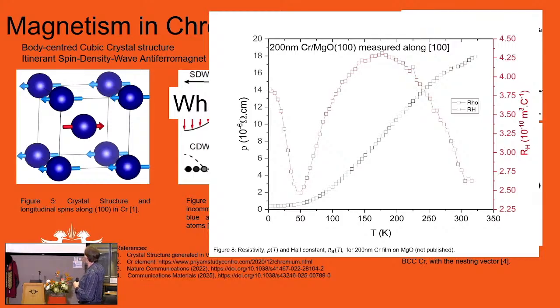And here we show resistivity, so current and voltage with a particular geometry. That's very important. But as you cool down, you take the heat away, and remember two things happen. And this is this little anomaly that you see. Now in chrome, the anomalies are typically very small. You really have to hunt for them in some of the measurements. What happens is, as the Fermi surfaces start to nest, you lose some of the conductors. And thus the slight increase here, where the spin starts to align. Of course, as you cool further, scattering of the electrons becomes less, and then you get this decrease.